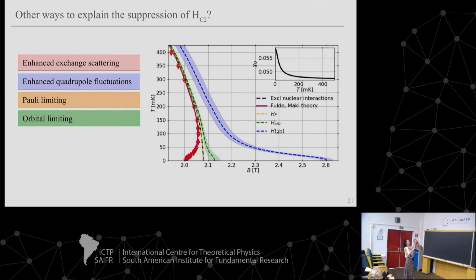We did consider other possibilities. So this is the enhanced exchange scattering scenario that I showed you with the good fit around here. We thought about what would happen with enhanced quadrupole fluctuations, so an enhanced quadrupole susceptibility. This is how the quadrupole susceptibility would look at 2 tesla, where the original superconducting transition was. And as I described already in words, because the AFQ phase is shifted to lower field, the quadrupole susceptibility would be enhanced at the superconducting phase boundary. So you would see an enhancement of superconductivity in this scenario, not a suppression.